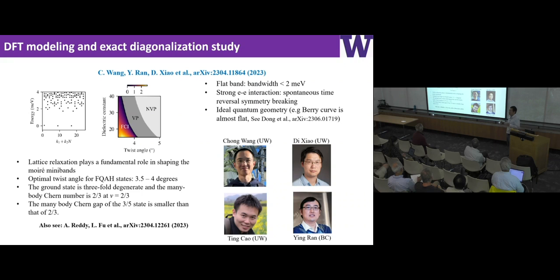So there are a lot of TMD systems proposed, and a lot of people ask me what's unique about MoTe2. One possibility is that the band is really flat, with a bandwidth smaller than 2 meV. Just to give you a comparison, for magic angle graphene the bandwidth is on the order of 10 meV. So it's already a flat band, but this is much flatter. The second is that there are very strong electron-electron interactions that give us these ferromagnetic states. And the third is that there is ideal quantum geometry. You can see what it means from Ashvin and his collaborators' paper.